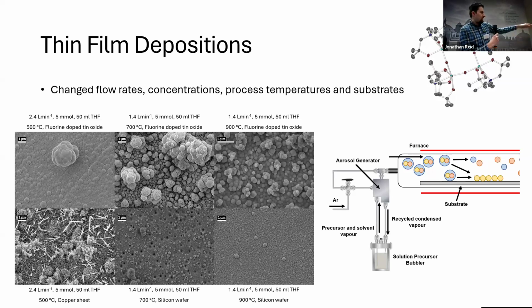On the bottom left, I have one where it looks like there might be some crystalline needles coming, and that's quite promising, but it turns out if you analyze them, they're actually just some copper oxide that's been created from depositing on copper. You can see my tantalum particles interspersed through there and not really interacting with that.